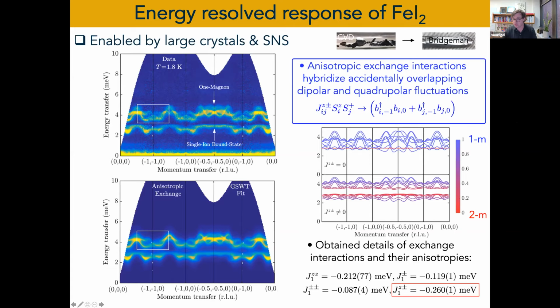My question is somehow related to Natasha's. When you are dealing with quadrupolar degrees of freedom, those are charge degrees of freedom, actually, so they have to be very strongly coupled to phonons, generally speaking. That's the unquenched orbital moment. You mentioned uranium dioxide, in which it's mostly phonons which are important. But what about your system? In principle, it should also be rather important here. Do you see any indication of that?